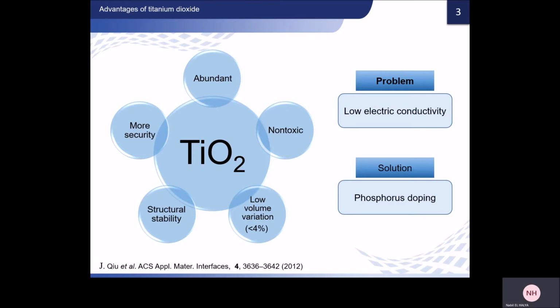A crucial disadvantage of anatase structure titanium dioxide is the low electric conductivity owing to its wide bandgap energy, a significant hindrance in lithium-ion battery anode material, resulting in dramatic performance decreases at high rates in the charge-discharge process. A doping technique is considered an efficient means of increasing the internal surface electrical conductivity. Doping with cationic or anionic dopants contributes to the formation of more open channels and active sites for lithium-ion transport via expanding interplanar spacing of titanium dioxide lattices.